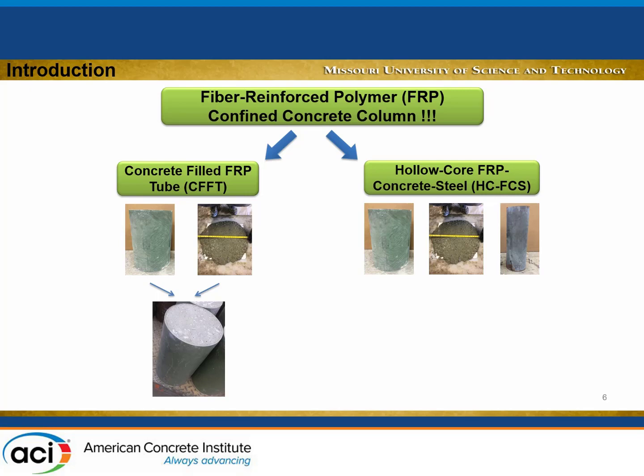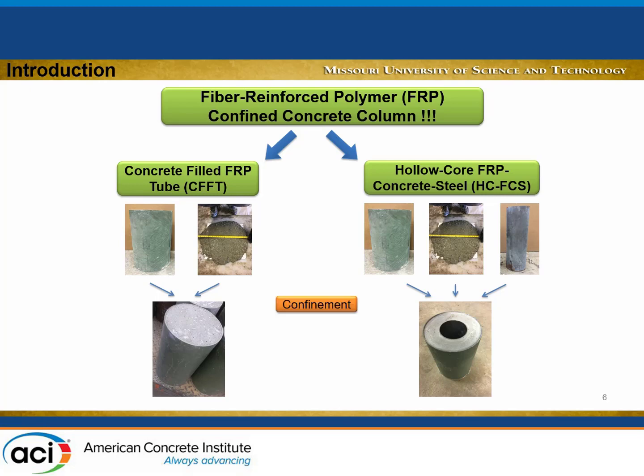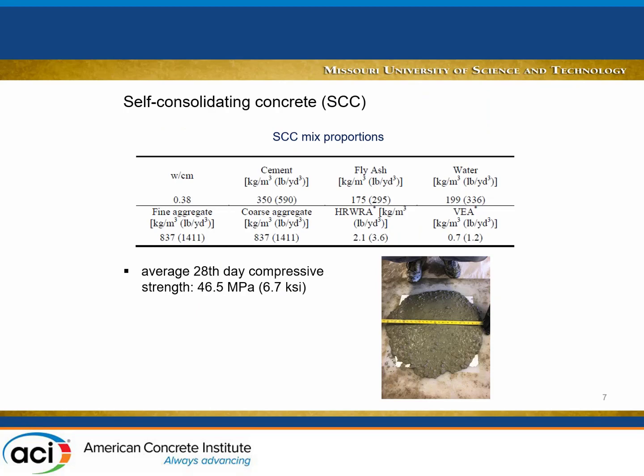A lot of people in the literature, you saw the first presentation in this session, did concrete filled fiber tubes under cyclic load. So what we think is a gap here is the durability of these systems. Most of them work very much to provide more confinement for your concrete. Actually, when we tested the larger scale of the system here, we reached 13% lateral drift with almost no damage to the columns. If you are interested in the self-consolidating concrete that we used, it's about 45 megapascal, slightly higher than what we typically use in Missouri, 7 KSI. We typically have 4 or 5 KSI.